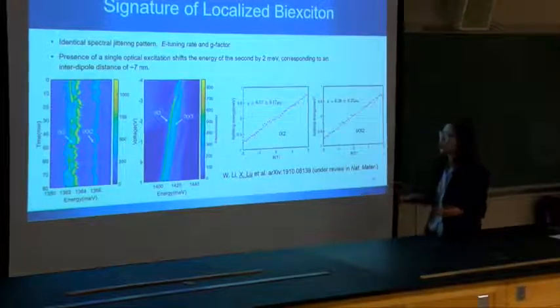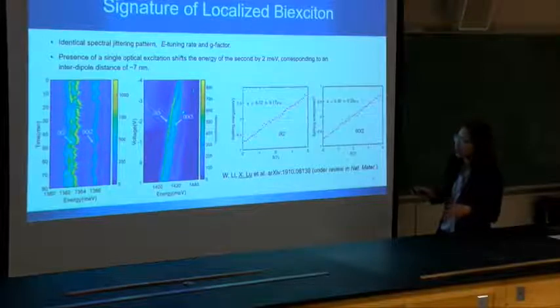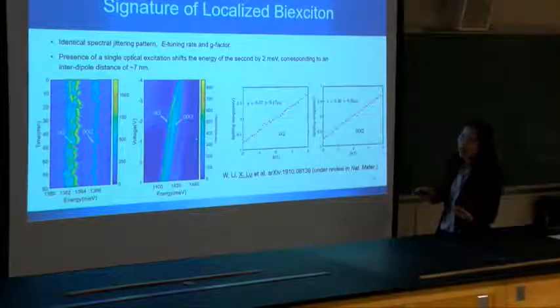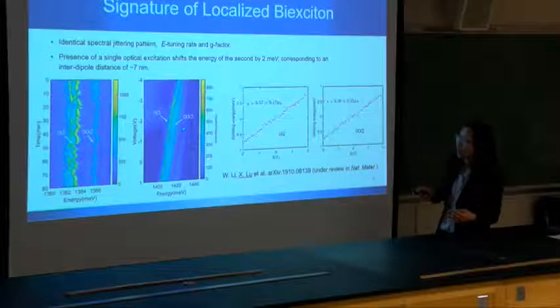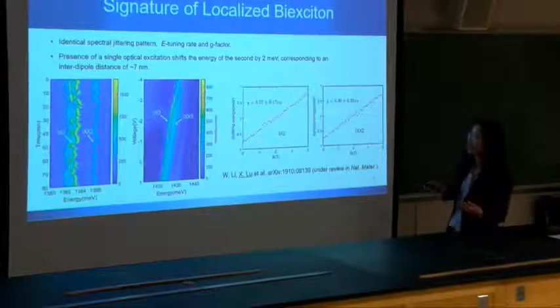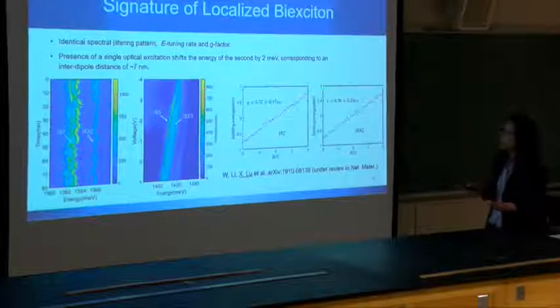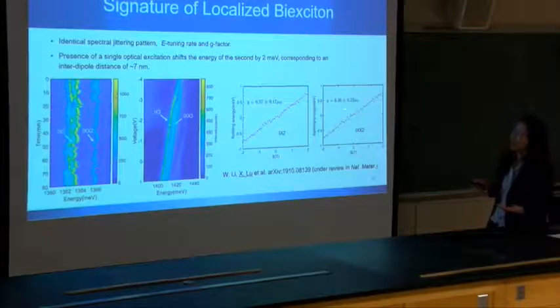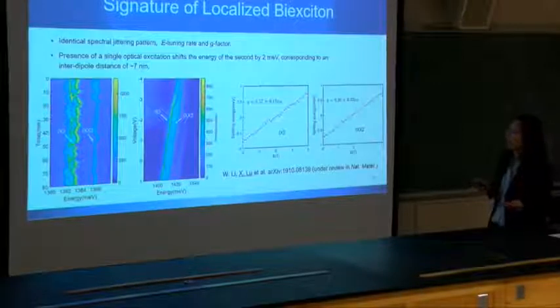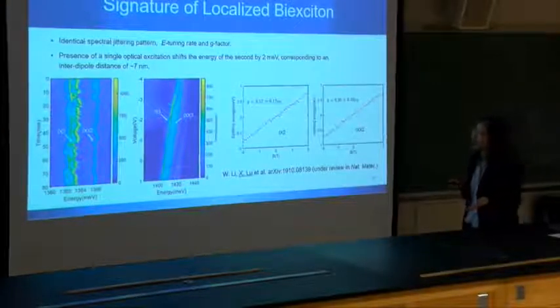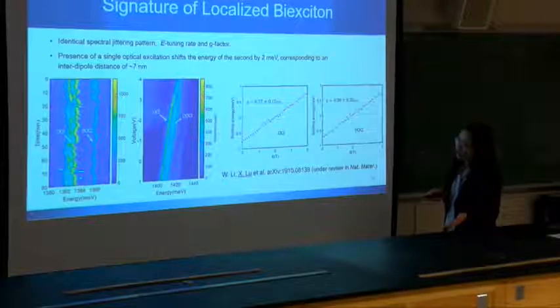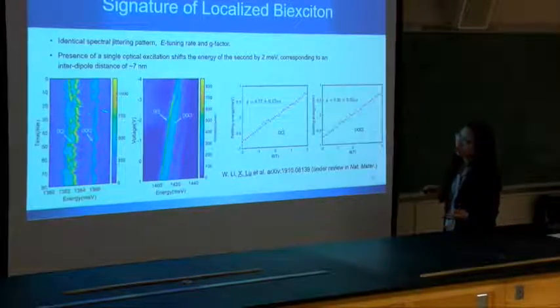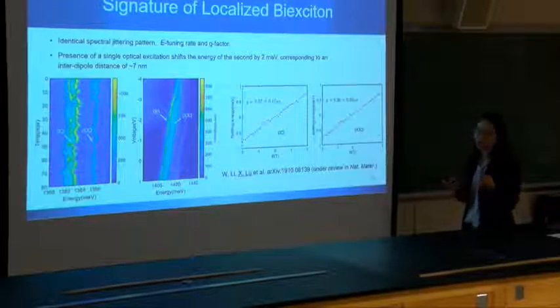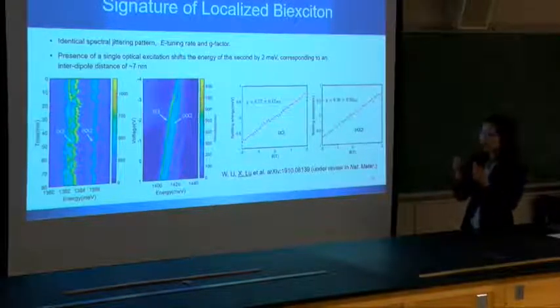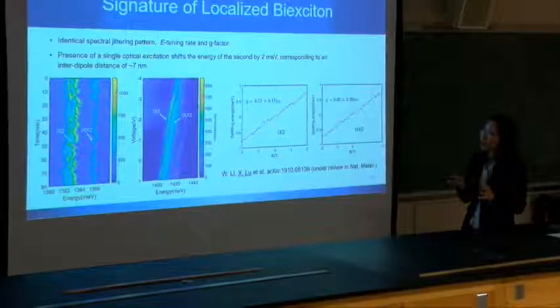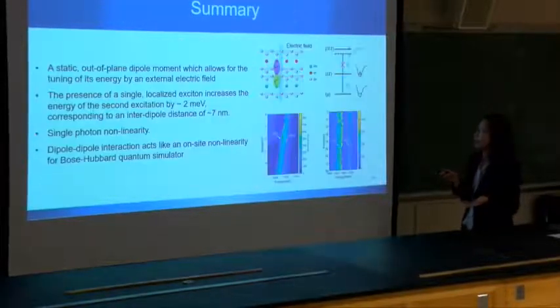And this is the tuning of the exciton and bi-exciton states, and as they have the permanent out-of-plane electric dipole, they can be tuned. And in terms of g-factor, we found that they also have the same value, which further confirms that they are the same species. And by extracting this energy difference, like 2 milli-electron volt, we did a simple calculation and found that these two dipoles in the potential well have an inter-dipole distance of around 7 nanometers.